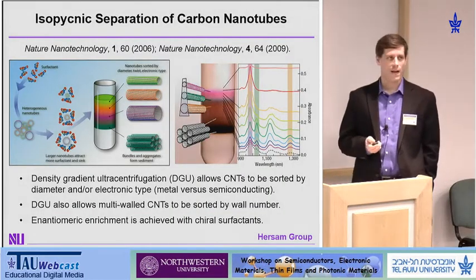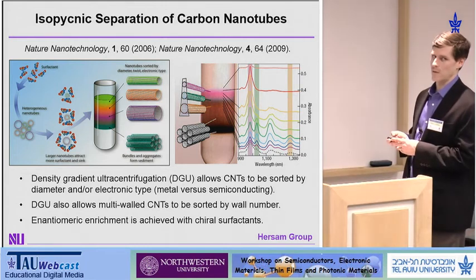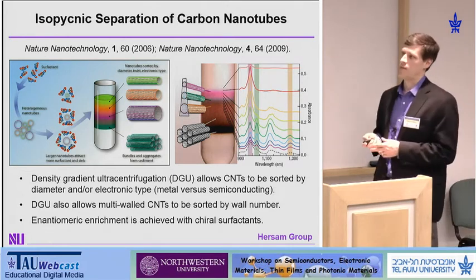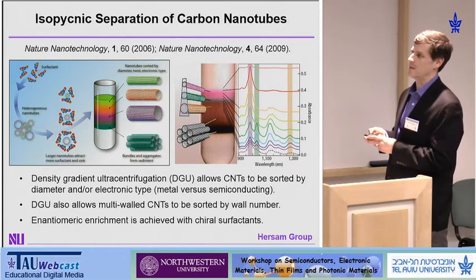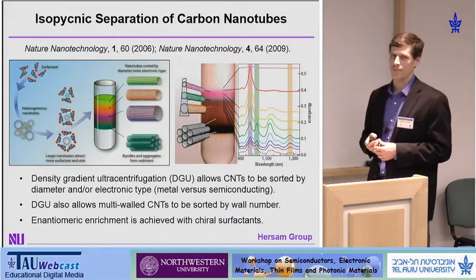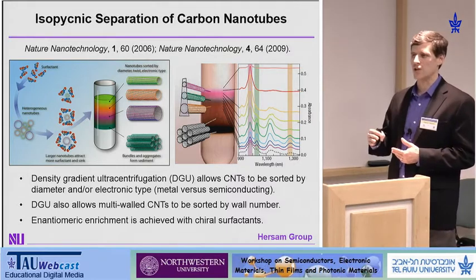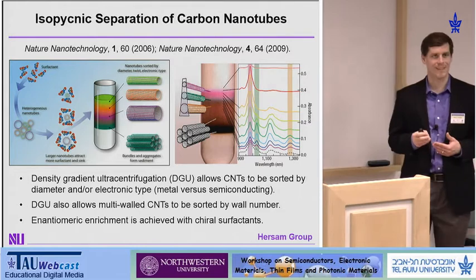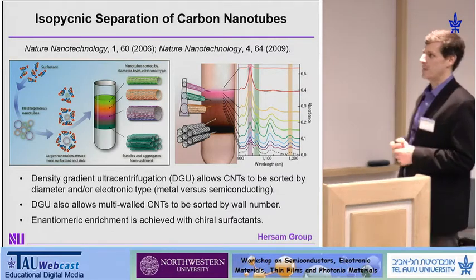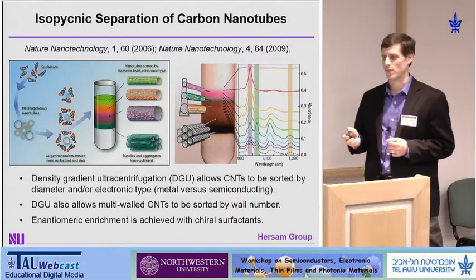The way we do this in our lab is to borrow a method from biochemistry called density gradient ultracentrifugation, or DGU. You load a centrifuge tube with an aqueous solution where you introduce an additive as a function of depth to tune the buoyant density of the solution — high concentration at the bottom gives high buoyant density, low concentration at the top gives low buoyant density. You then load a nanomaterial population dispersed with appropriate surfactants and turn on your centrifuge. That drives sedimentation through the gradient until your nanomaterials reach the isopycnic or equal density point and simply float. This method separates your nanomaterials by buoyant density and, since buoyant density depends upon size and shape, allows you to separate materials by those parameters.